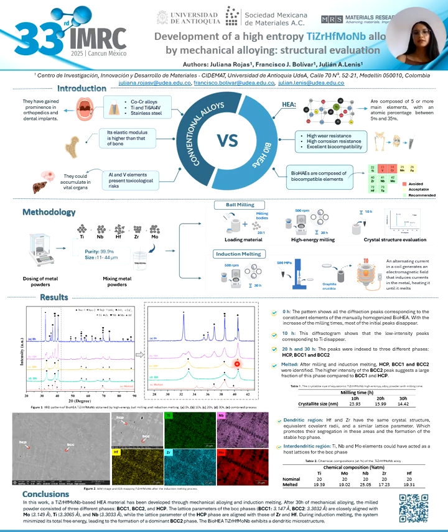These patterns show that the low intensity peaks corresponding to titanium disappear, due to the fact that elements with lower melting temperature tend to form a solid solution phase before those with higher melting temperature, as a result of their higher diffusion capacity.